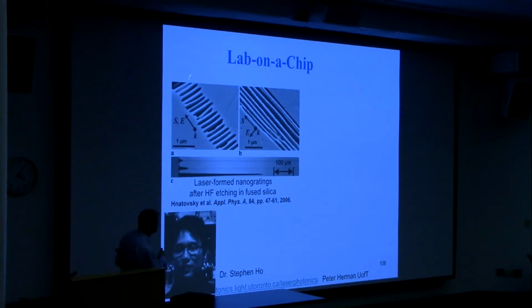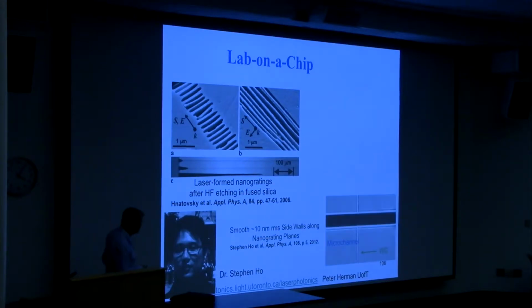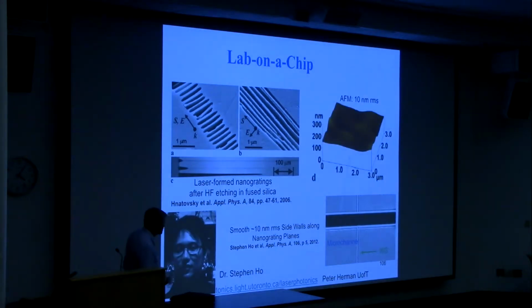So you can open up these tracks, particularly if you align the gratings this way, and do buried channels. So that was this sort of work done from Ottawa, and many groups, including our group, have picked up on it. For example, this is a buried channel in fused silica glass where we form these nanogratings and open them completely, but then we also, by running devices this way, could form waveguides that would not etch. And so we now have a microfluidic device with optical sensors integrated together, and you can integrate these in 3D.